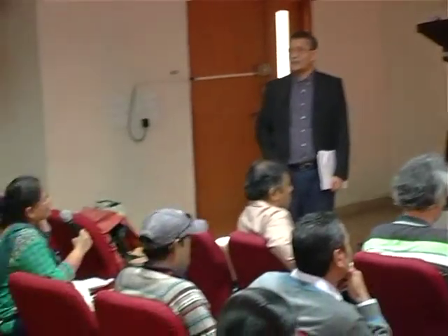Going on in the same line as everyone has been talking about, we've done some recent work on some early transition metal oxides. I think this effect should be coming from the U on the oxygens. When you talk about a large U in a pd model, everyone talks about a large U on the transition metal site, which is something like 7 to 10 eV. In that same model, you evaluate the U on the oxygens, it's about 7 eV.